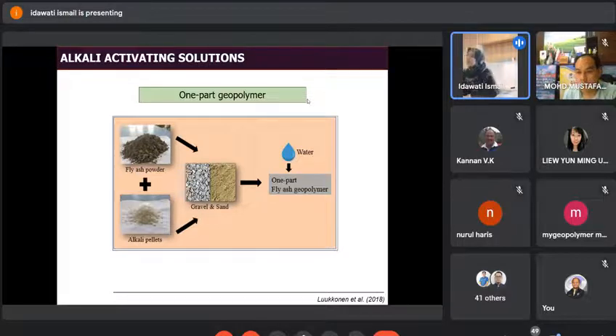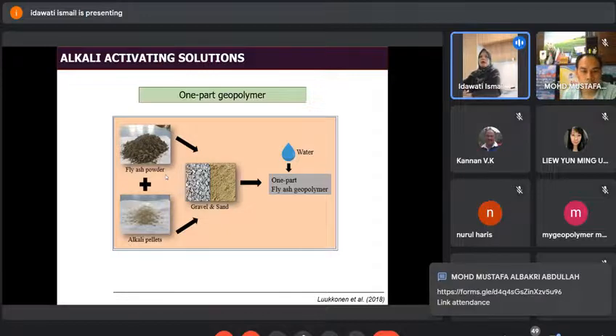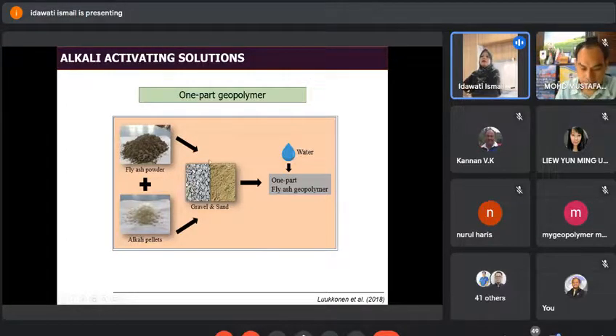Now, I want to highlight another type of mix, which is one part geopolymer. I think maybe UniMAP has started doing something like this. In the first slide that I showed you just now, a geopolymer is mixed with fly ash and mixed with alkaline solution, right? That process is actually quite hazardous, because the solution is very corrosive, and if we want to bring solution, it's very hard to work on site, for example, or if you want to work with a very large amount of concrete. So this is also quite current, probably the last 7-8 years.